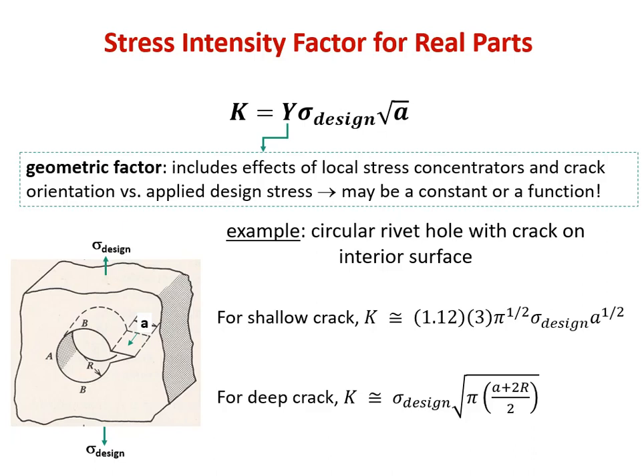So if you have a shallow crack coming off of a circular rivet hole, it will have a K that's equal to 1.12 times 3, both just constants, times pi to the 1/2, times your applied design stress, so you can see this being applied to the whole plate, times the crack length, not the whole radius, the crack length raised to the 1/2. So if you look at that 3, that should look really similar to the stress concentration factor for a circular hole. So the Y in this case would be 1.12 times pi to the 1/2 times 3. So this would include the effect of the hole to begin with, and it would include the effect of the crack and its orientation to the applied stress.